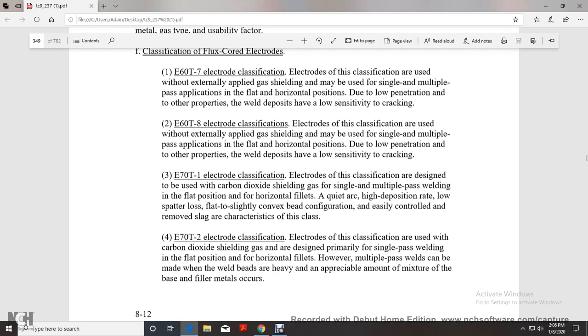The E70T-1 electrode classification is designed for use with carbon dioxide shielding gas for single and multiple pass welding in the flat position and horizontal fillet, with a quiet arc, high deposition rate, and low spatter loss. The weld bead is flat to slightly convex with a bead configuration, easily controlled, with easy removal of the slag, which has the characteristic of this class.